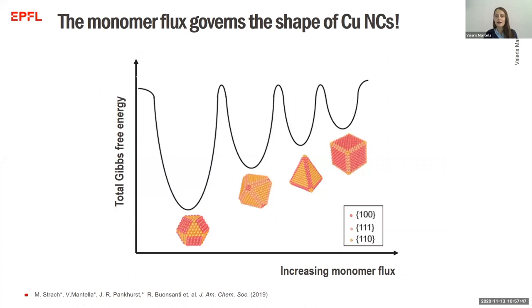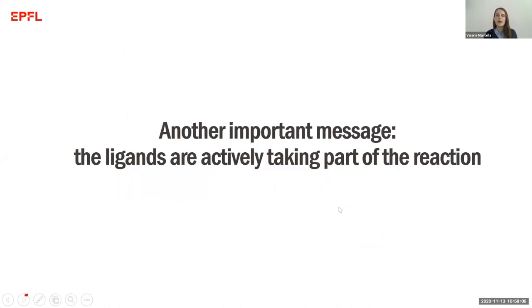So back to our diagram, we can now label the x-axis as the increasing monomer flux, since this is the key parameter in order to move from thermodynamically to kinetically driven products in the energy landscape of metal nanocrystals such as copper. Another important point evidenced in our study is that ligands are actively taking part in the reaction.